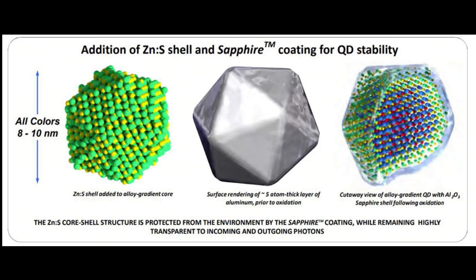So sapphire is one form of aluminum oxide. So they're adding aluminum oxide to the surface, and the idea there is that aluminum oxide might make this system a little bit more robust by protecting the quantum dot from any oxygen that reaches its surface. One thing we haven't discussed yet is that quantum dots, the reason they've taken a long time to come to fruition, is because they're really sensitive to oxygen. And so if you make them and leave them exposed to air, they will not last long enough to be in a consumer display. So they have to be protected in some way, and this is one way that people are looking into trying to protect these quantum dots from oxygen, is putting some sort of metal oxide, aluminum oxide, or glass around the quantum dot in order to protect it from atmosphere.